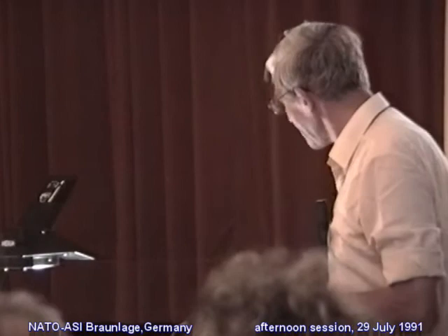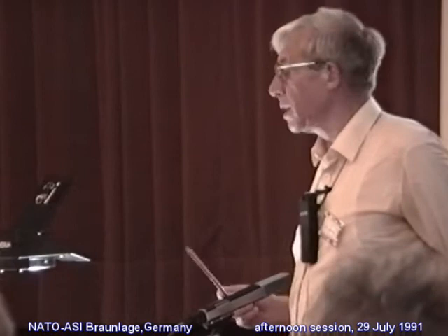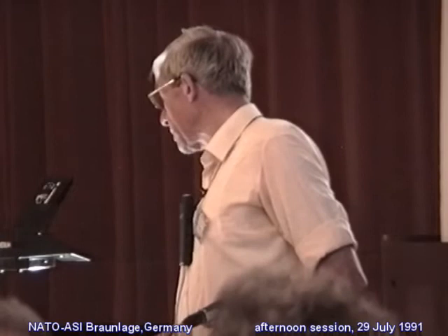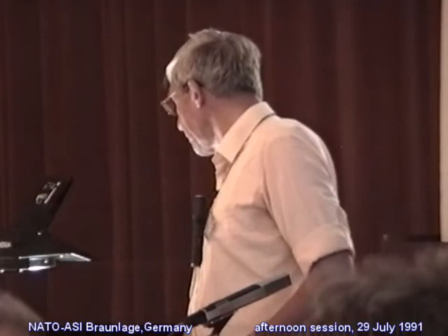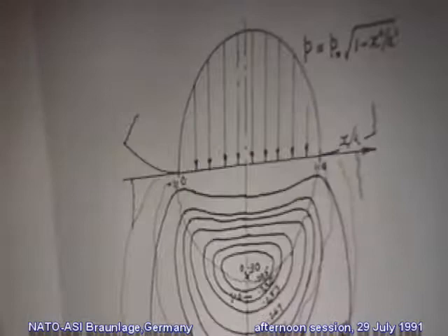We got to the point of Hertz producing a pressure distribution, a maximum pressure in terms of load, geometry, and elastic properties, and discovering that, somewhat surprisingly, we take it for granted now, but surprisingly, the yield occurs at a point beneath the surface. I say to my undergraduate students who've done elementary structural mechanics problems, where else have you come across a situation where first yield occurs below the surface? And it's hard to think of any others.